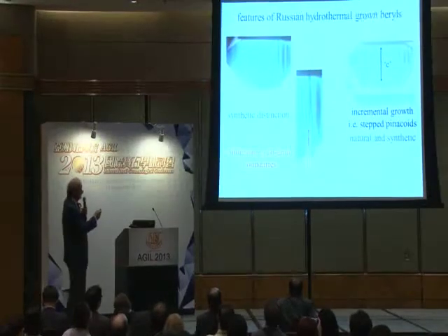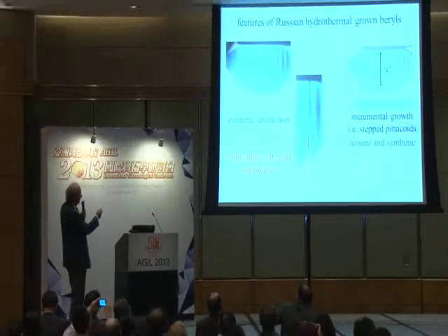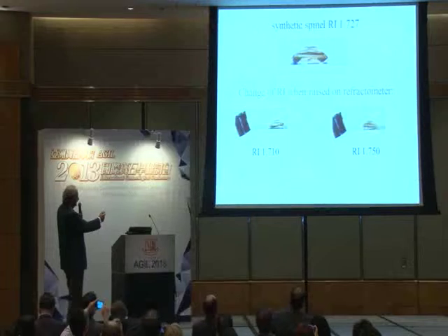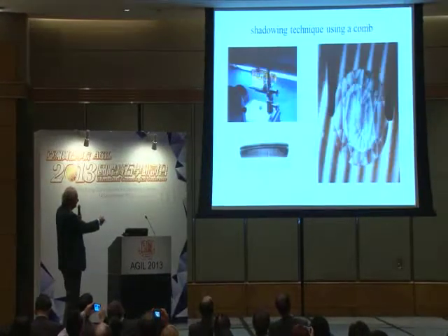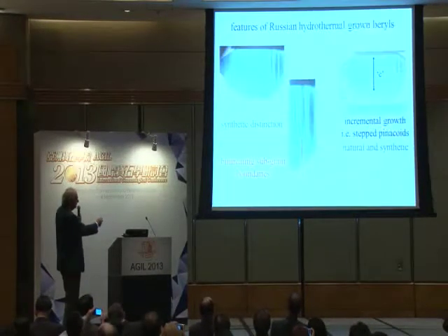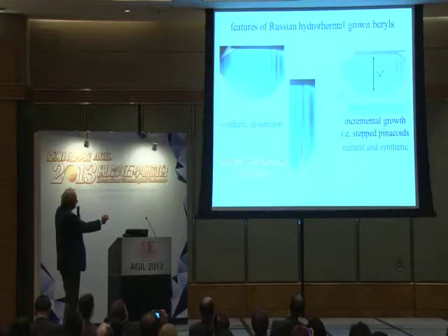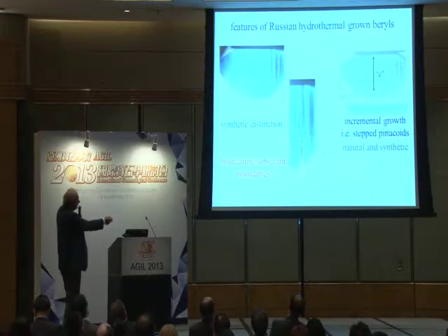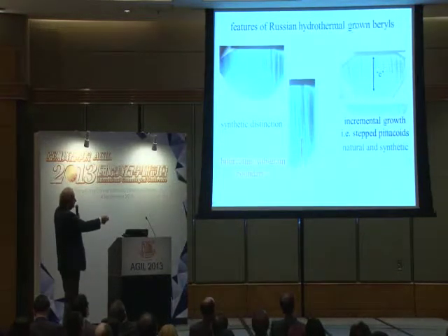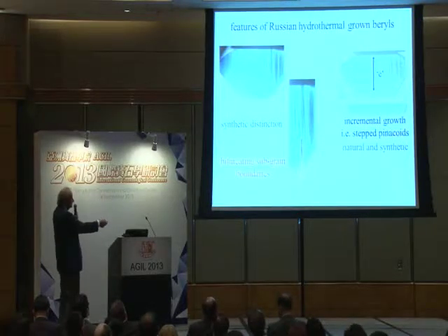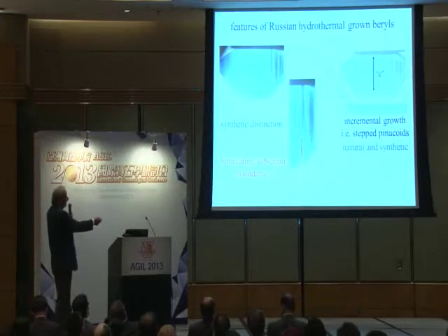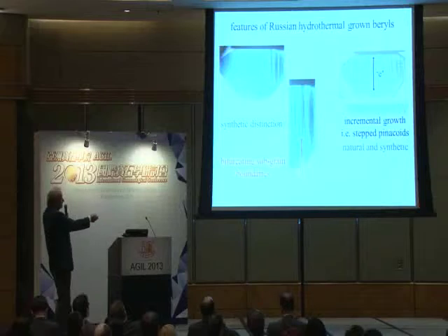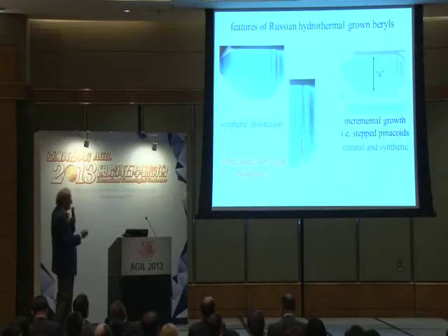Not only is there that subgrain boundary that we see here, it's like a bifurcation effect, but you also see pinacoidal developments. But be careful, because we see these on natural emerald and aquamarine as well. It's these bifurcations on the C-axis that give the game away.